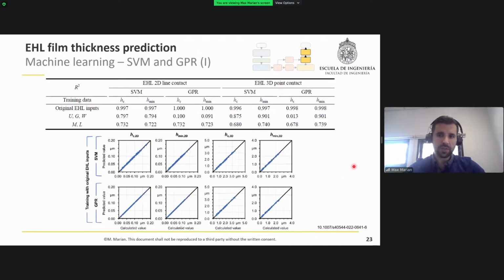Okay, so finally, let's check out some results. We start with the prediction from the support vector machine and the Gaussian process regression. There's a lot going on on the slide, but I will try to guide you through. In the table, we can see the R square values, always against the testing data. And in the graphs at the bottom, we can see the predicted value versus the calculated value. The closer R square gets to 1 and the less deviation from this 45-degree line we have, the better is the prediction accuracy of both approaches.